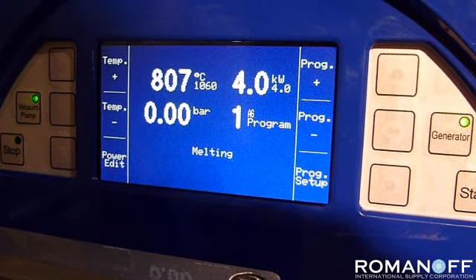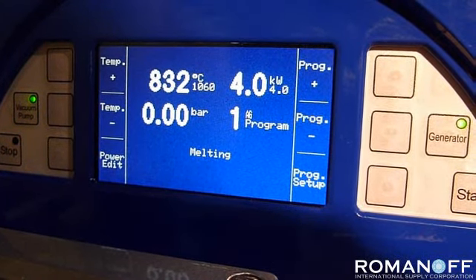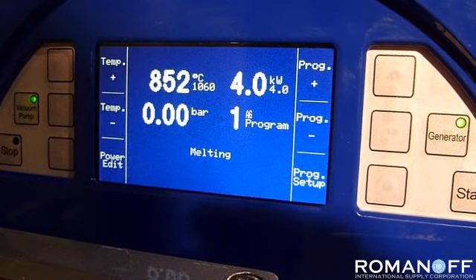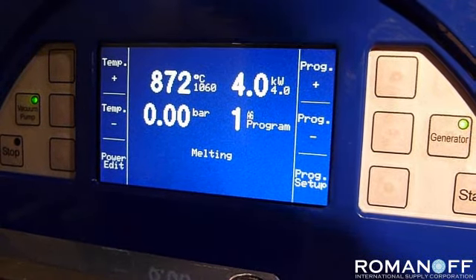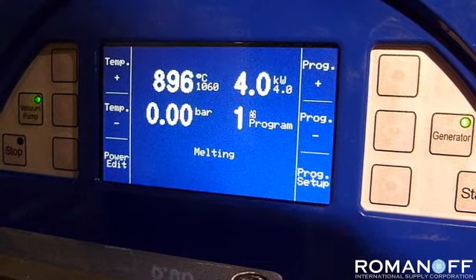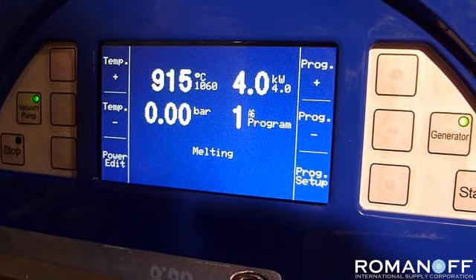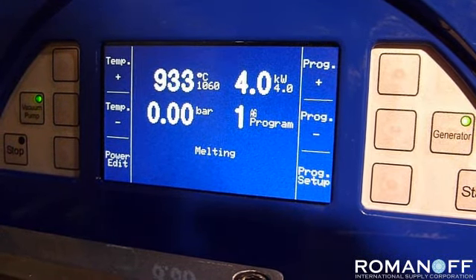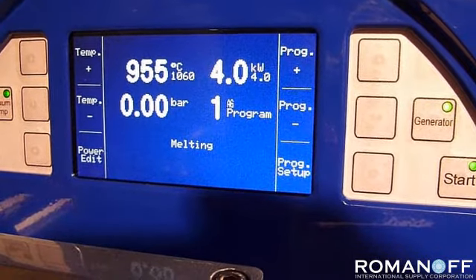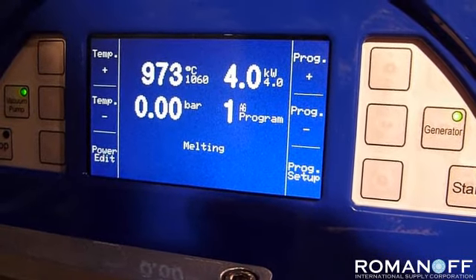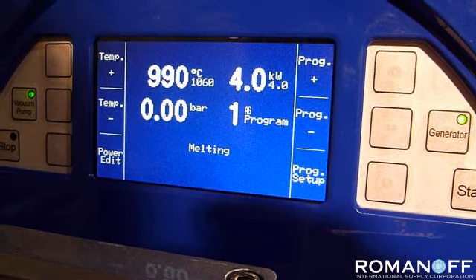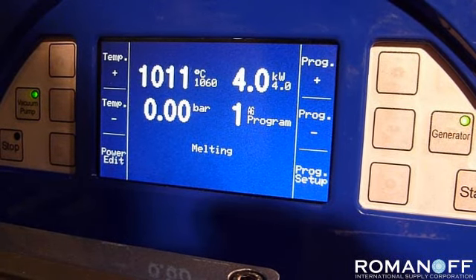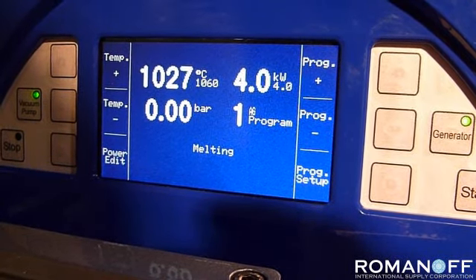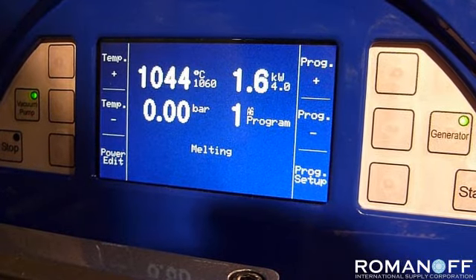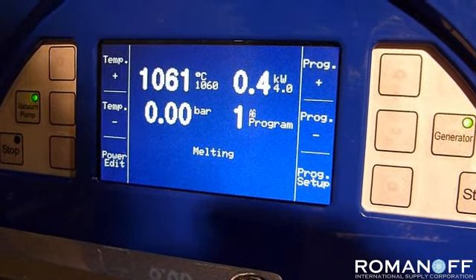There is an optical pyrometer which is used for the higher temperature range metals, platinum and palladium, and an immersion pyrometer for up to 1300 C, which is for gold, silver, and brass alloys. The immersion pyrometer is an extremely accurate method of measuring the temperature of molten metal, and this particular very sophisticated optical pyrometer gives you an accurate control over your higher temperatures of platinum and palladium and so on.